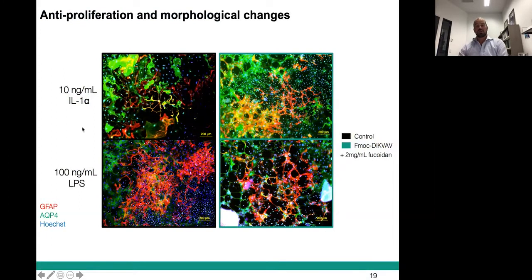So then what we did is we actually wanted to have a programmable inflammatory model of the brain. So Francesca took this back outside the body again. We cast these gels into a chamber slide and then put the astrocytes either underneath them, on top of them, or within them. And then we can challenge them with things like interleukin-1 alpha, LPS, just to really make them activated like a real injury state. And then when we have this fucoidan present, we can actually start to program the systems and turn inflammation on and off just by putting these soluble molecules in. And you can see they switch.